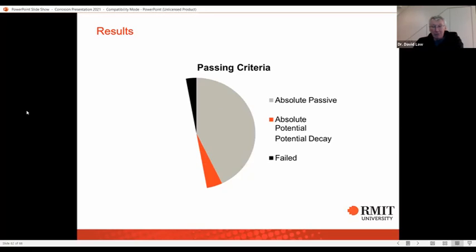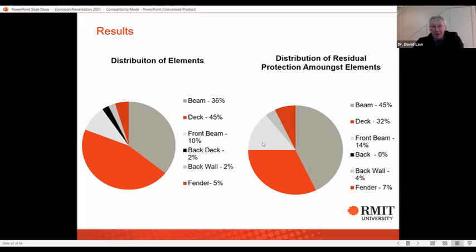And why do we get some that fail after a period of time? So we looked at the elements, and we could look at the beams, the deck, the front beam, the back deck, the back deck wall, and the fender beams when we looked at overall. And we can see it was distributed fairly evenly amongst those elements. So this is the total amount of elements that we looked at for each of those.